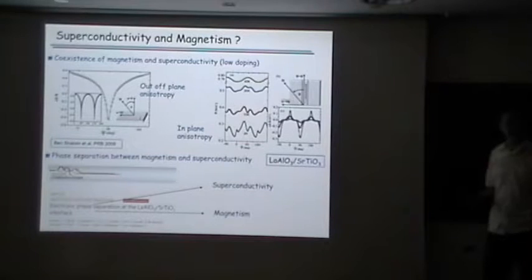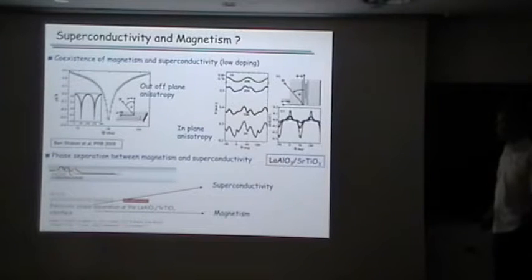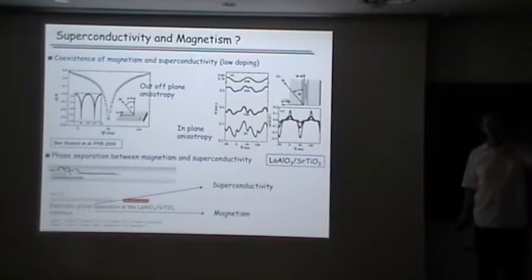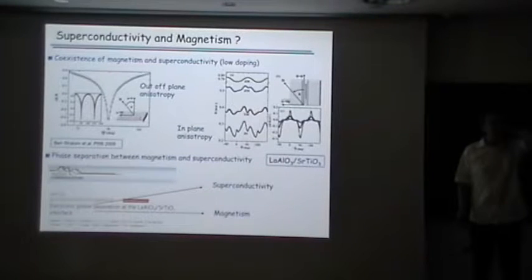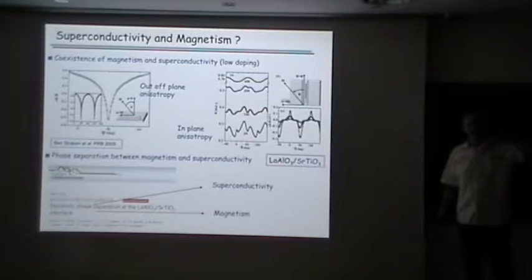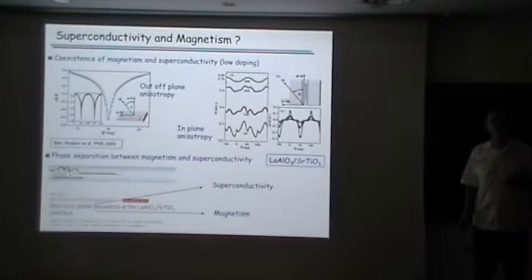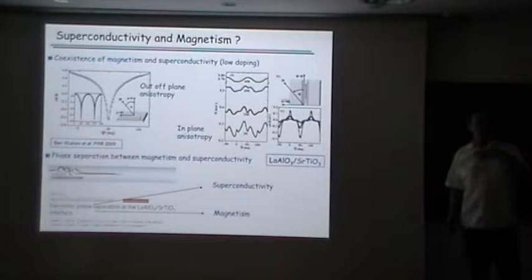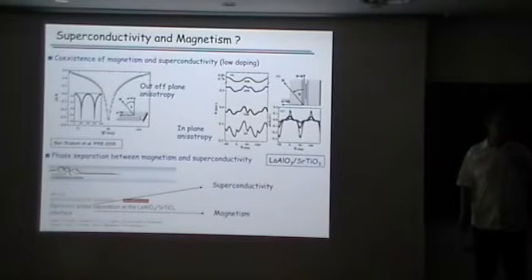And even most recently, people are claiming that you may have coexistence of magnetism and superconductivity in the same samples, which in principle is very interesting. But if you look into the details, again, these are very high pressure grown systems and very inhomogeneous. I don't think if you make a TEM cross-section of those systems, you can find these very well-defined interfaces I was talking about. So I think it's still an open question if there is also magnetism in the system, but I'm not sure it's completely under control. What is under control is the high mobility gas and the superconductivity.